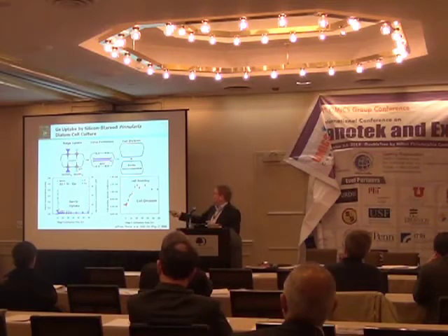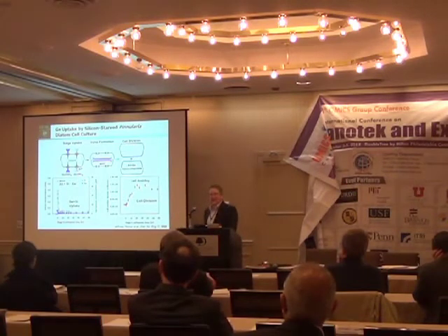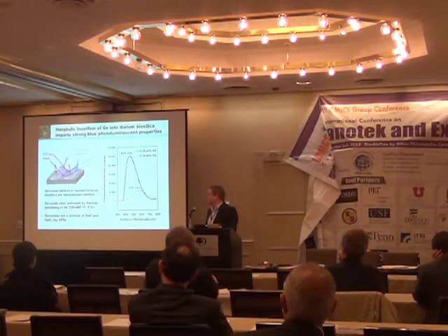So shown here, the organism takes up silicon. That silicon is used to make a second shell for each side so that when the cell divides, a new shell is formed. If we add in germanium concurrently with this silica being formed, we can actually make a silica-germanium nanocomposite on one side of the organism. And we can design, like I said, the composition associated with that.